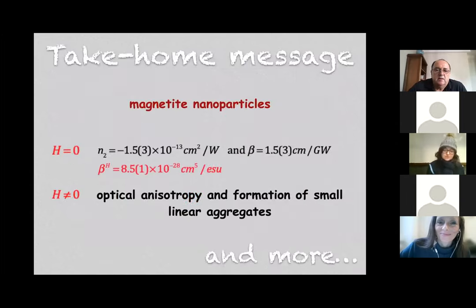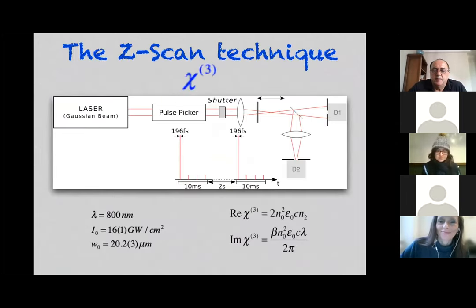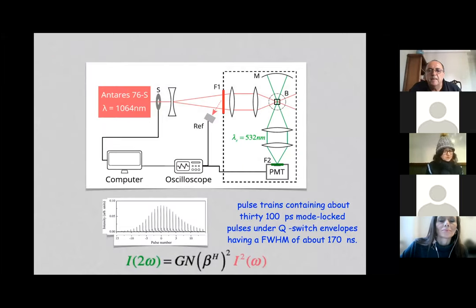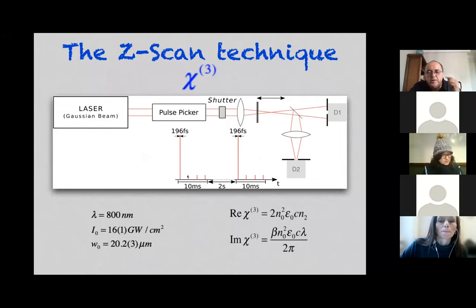Yes. This was a concern that we have when we do this type of experiment in the Z-scan experiment or even in the hyper-Rayleigh. You see that here we put about a 200 femtosecond laser beam shining the sample. This laser gives several pulses of 200 femtoseconds. With the pulse picker, what we have is about 99.9% difference in intensity between this peak here and that there. But we saw that even with this 99.9% less intensity of the beam, if you take a lot of them, your sample will heat.